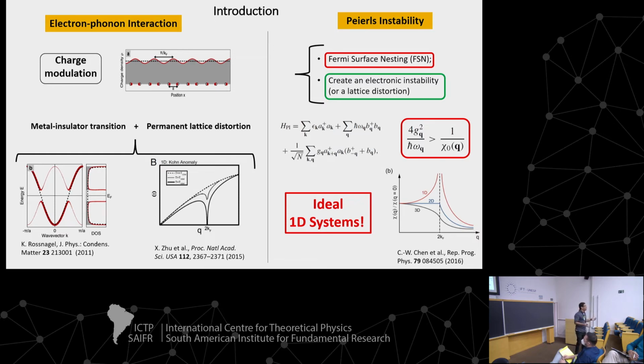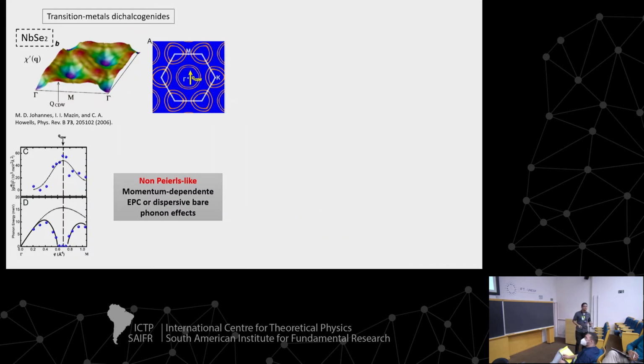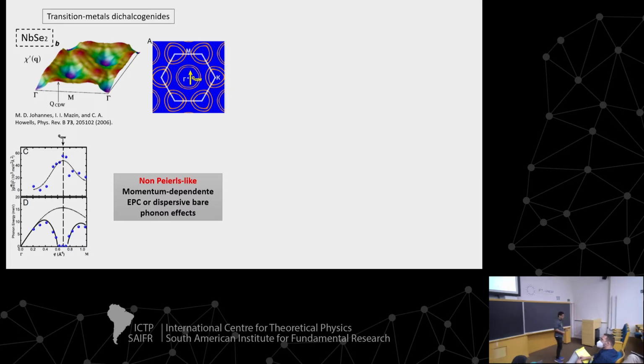But this is not the whole story, because there are many materials that do not follow this Peierls mechanism. For instance, the transition metal dichalcogenides have strong electron-phonon interactions, but they don't have Fermi surface nesting, yet they present charge density wave. One example is niobium diselenide. So this is not Peierls-like, but it's driven by electron-phonon interaction. There are many other features about the electron-phonon interaction that we don't know, and this should be analyzed.